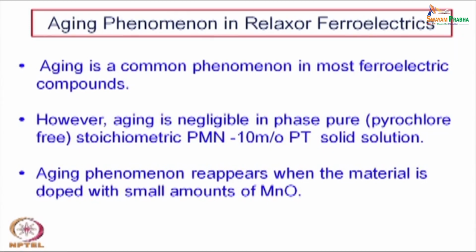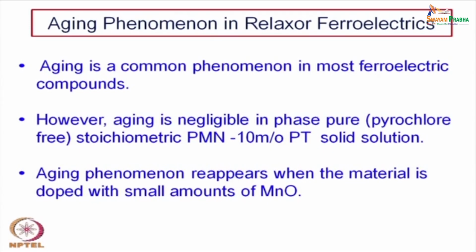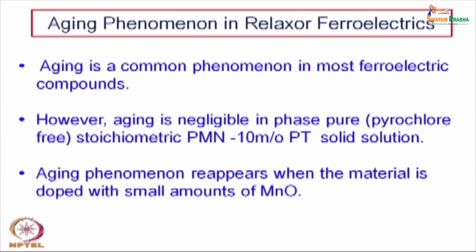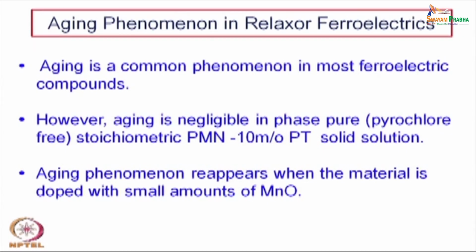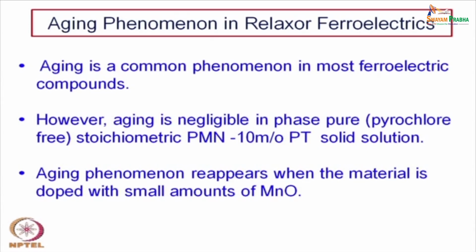It is completely pyrochlore free, pure perovskite, a solid solution, and that aging property is almost negligible. So, with time the property really does not change. However, the aging phenomenon may be there once it is doped with a small amount of MnO.